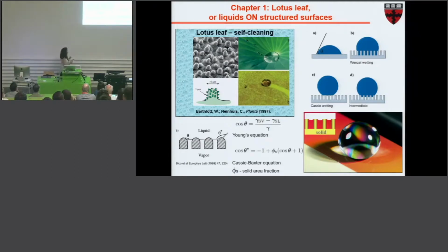So the function of structure, with any chemistry that gives it hydrophobic character, is that the droplets will sit in the form of almost spherical droplets, and therefore they have the ability to roll off this surface, pick up the dirt, and in this way clear the surface. So the contact angle, the one that you consider for the surface, is a complex angle that is composed of solid and liquid fraction.